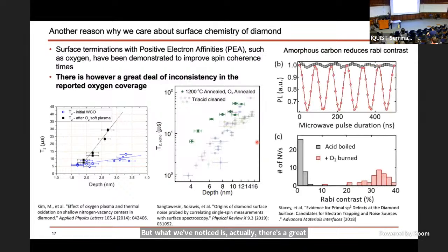And here's one more piece of information that we'll come back to later, is that in addition to just oxygen content on the surface, which gives you positive electron affinity, there's also the observation that any graphitization or amorphous carbon on the surface is going to affect your spin behavior. We'll go back to that later.